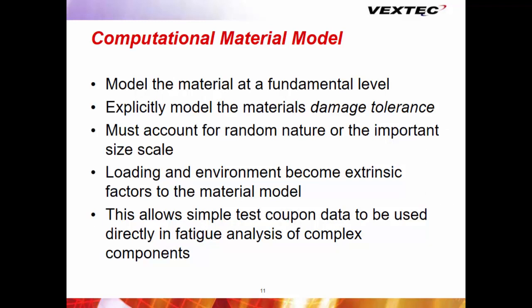And these computational material models actually try to model the material at some fundamental level. So if slip is driving things, let's look at slip. If voids are driving things, let's populate with voids. If it's voids and slip, put all of those fundamental discontinuities in the model and let damage grow from each and every one of those in this system reliability type model. So it's important that we get the randomness. Size is very important. The larger something is, in general, the lower its life is.